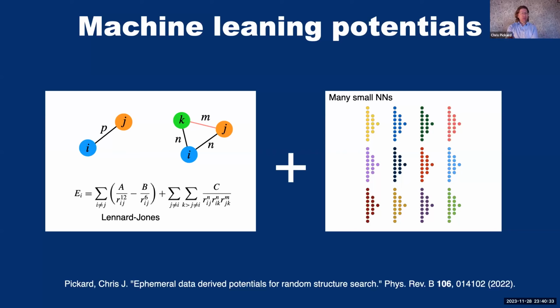Now, Lennard-Jones has a two-body term which describes the interactions between pairs of atoms, and then you have a repulsive term that has a 1 over r to the 12 form, and an attractive term that is 1 over r to the 6. Now, this is a two-body contribution to the total energy, and is good maybe for binary or ternary systems. But if you have an elemental system or a system exhibiting strong covalent bonding, this two-body term is not likely to give you a good description. So I went one step further and I wrote down what I would think Lennard-Jones might have written down to describe a three-body interaction, where I consider the interaction from a central atom to two neighbors, and also between those two neighbors themselves. And essentially what this three-body term is doing is allowing an angle to open up between pairs of bonds.